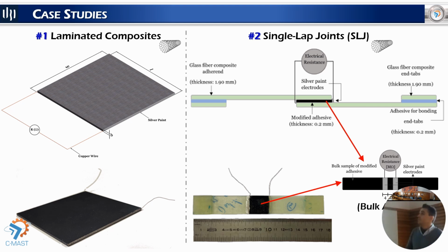So moving into the experimental results, I will present two case studies that we implemented in laboratory experiments. We studied this solution in laminated composites, which are typical composite materials used, for instance, in aircraft and airplanes, and also in single lap joints, which is a solution very common also in aerospace structures, in cases where the bonding of some components should avoid screws or holes that can compromise the structure. So we applied this concept of piezoresistive self-sensing in these two case studies.